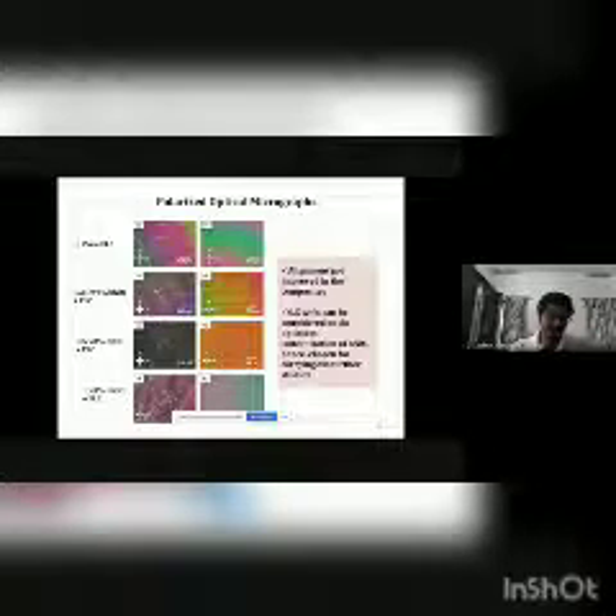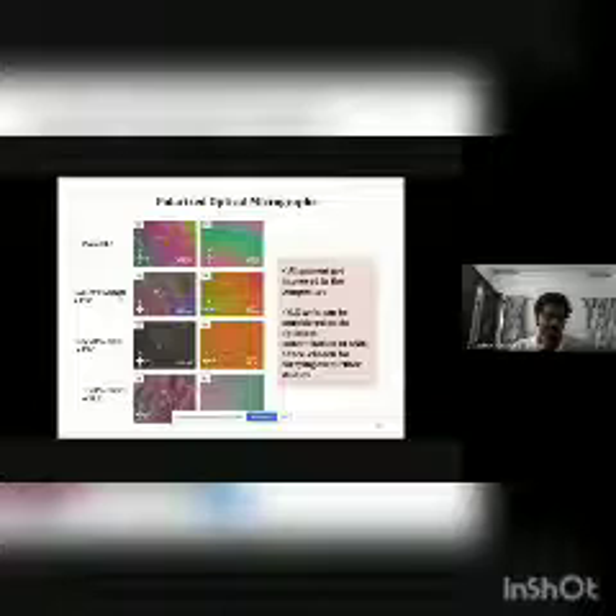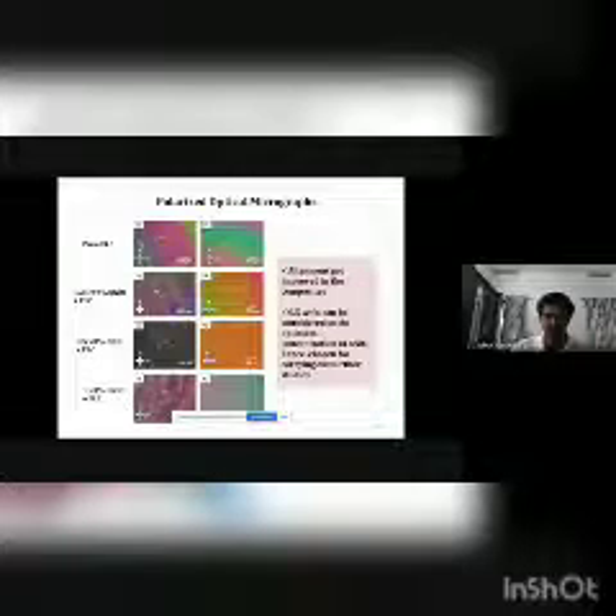So we have prepared 4 different samples. One is of pure FLC, and in other 3 we have added different concentrations of nanomaterials, 0.25, 0.5 and 1 weight percentage. And these are the dark states and these are the bright states corresponding to those display devices. In case of pure FLC, you can see that the dark state is not completely dark. There is a lot of disturbance in this alignment.